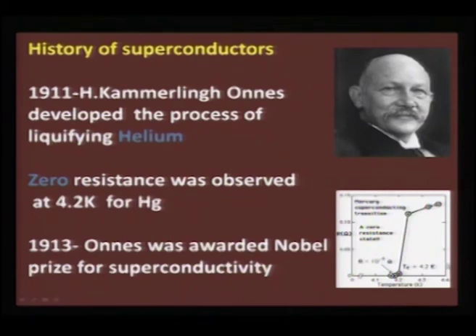This is one of the first results from Kamerlingh Onnes, where you can see there is a metallic state as you cool the mercury, and at 4.2 K there is a sharp drop in the resistance, to the order of 10 power minus 5 ohms. A zero resistance state is achieved. As a result, mercury behaves like a superconductor, and as you know mercury is one of the metals existing in the liquid state. So there have been a lot of studies on other metals.